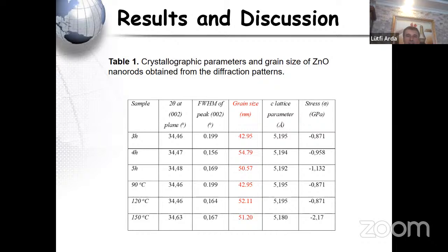Also in Table 1, there is the full width at half maximum. The shrinkage of the width of the peaks with growth time and temperature increase indicates a particle size increase.